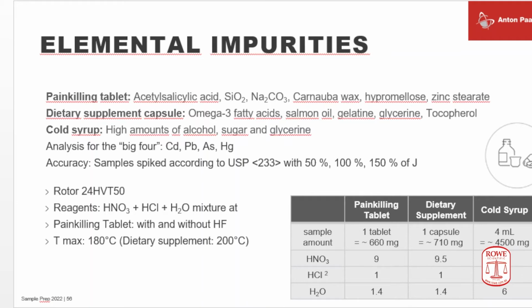Pain-killing tablet, dietary supplement. What you could see with the cold syrup is a bigger portion of water added to the solution. Why that? Because with this water we are somewhat diluting the alcohol in the sample, because the alcohol would react very, very violently with the nitric acid at elevated temperatures. So sometimes it is necessary to reduce the oxidation strength because the instrument would be very powerful in heating, and in order not to react a certain sample too violently, we reduce the reactivity by the addition of water.